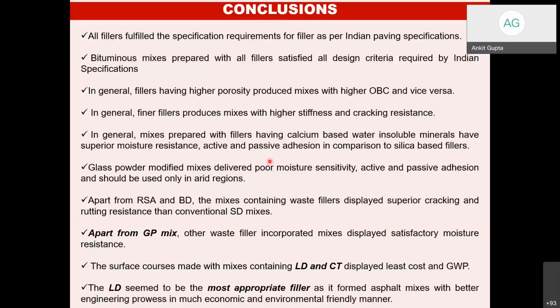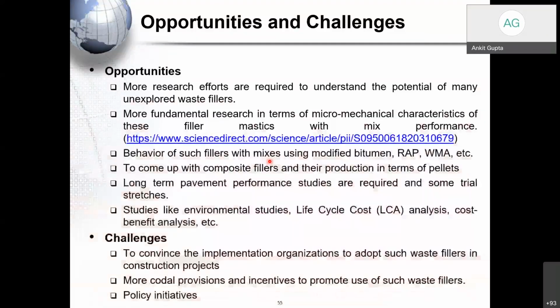The limestone dust seems to be the most appropriate filler because it has a high calcium content. It is a finer filler, so we get a more compact structure, and it forms asphalt mixes with better engineering properties in a more economic and environmentally friendly manner.